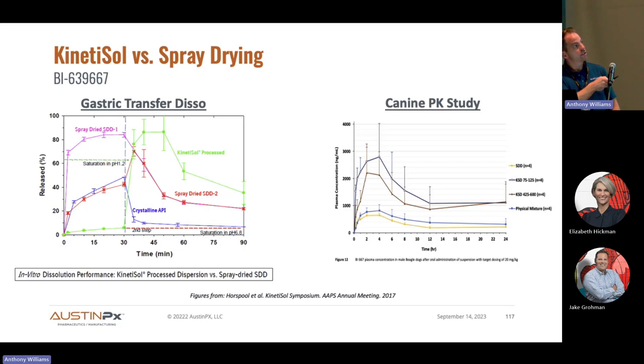And then as you transition into the neutral phase, this version of the spray dry dispersion begins to precipitate almost immediately, while this one shows some spring and then followed by fairly rapid precipitation. The KinetiSol formulation springs into solution. There is obviously a parachute effect, doesn't quite hit that spring and plateau that Dana was talking about earlier, but begins to precipitate. So you start to see the in vitro differences that start to lead you down the path of a hypothesis as to why KinetiSol is routinely outperforming spray dry dispersions.